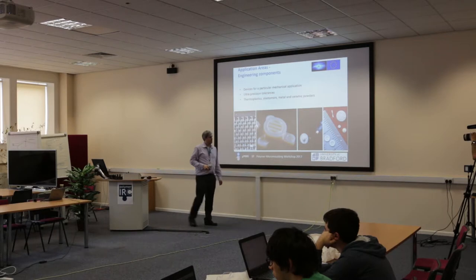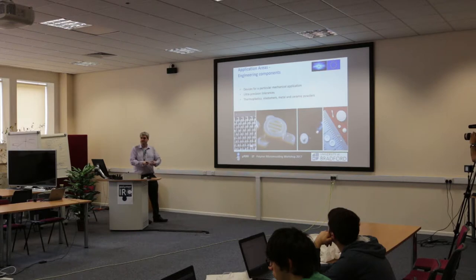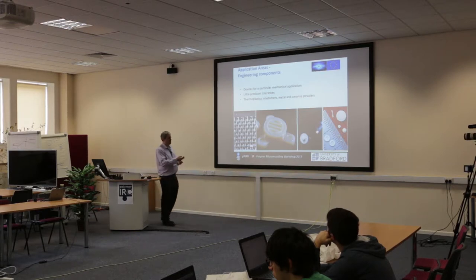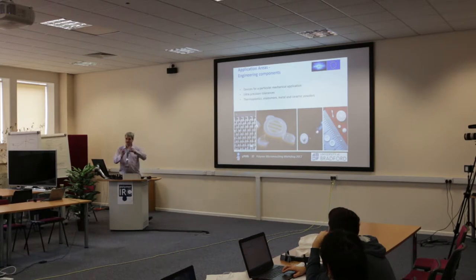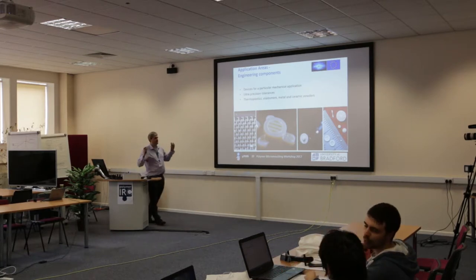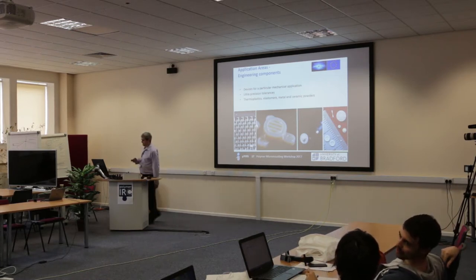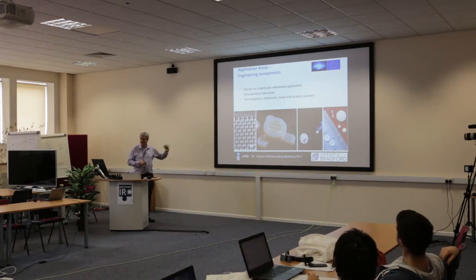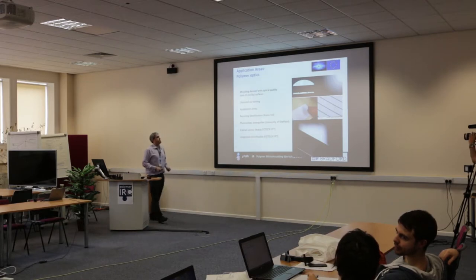We can also use different materials like metal and ceramic powders. Work with collaborators at Karlsruhe Institute of Technology and at Bradford uses ceramic-filled powders — we fill the tool with ceramic powder and polymer binder, place it in a furnace to remove the polymer binder creating a ceramic scaffold, then sinter that component to make a final approximately 98% solid ceramic part. This gives us the capability to use different materials for different applications.